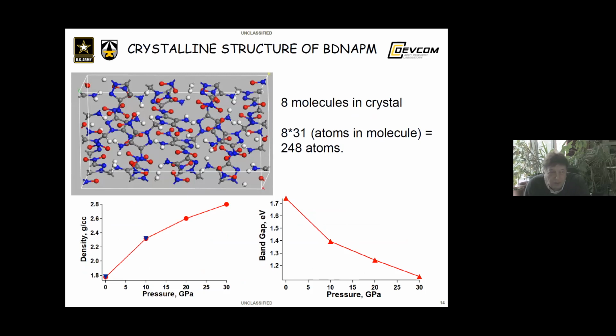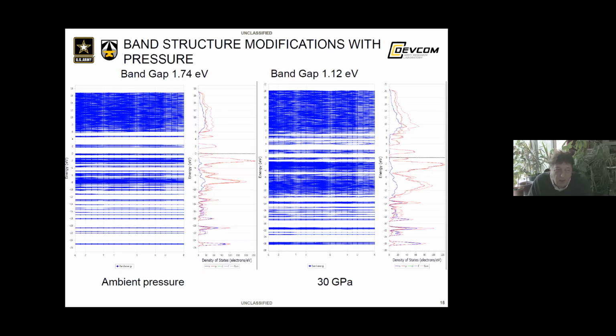What happens with the BDNAPM under high pressure? Mass density is obviously increasing upon compression and decreasing upon decompression. Band gap is also decreasing. Here's the band structure of BDNAPM at ambient pressure and at 30 GPa. Here's the band structure and density of states, red P states, blue S states. This is a band gap. The band gap is decreasing significantly, but far from closing.